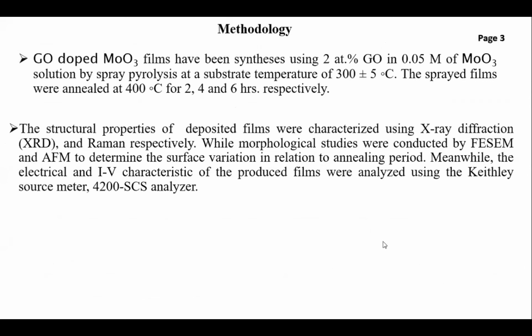Graphene-doped molybdenum oxide films have been synthesized using 2 atomic percent graphene in 0.05 molar molybdenum solution by spray pyrolysis at a substrate temperature of 300 ± 5 degrees Celsius. The sprayed films were annealed at 400 degrees Celsius for 2 hours, 4 hours, and 6 hours respectively. The structural properties of the deposited films were characterized using X-ray diffraction and Raman spectroscopy, while the morphological studies were conducted by FESEM and AFM to determine the surface variation in relation to the annealing period. Meanwhile, the electrical and IV characteristics of the produced films were analyzed using a Keithley source meter.